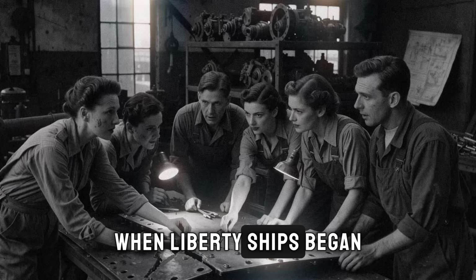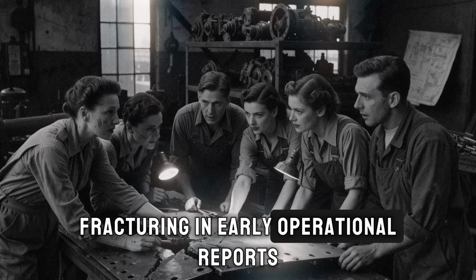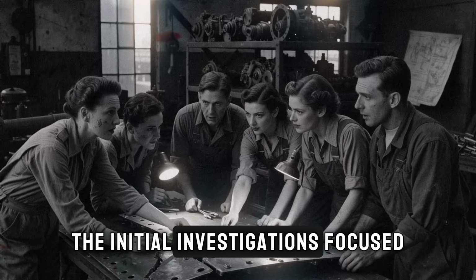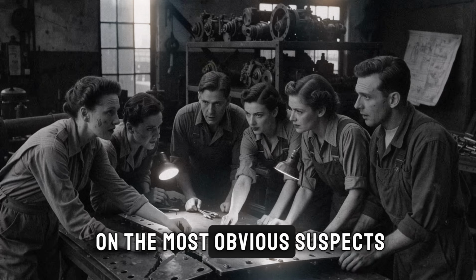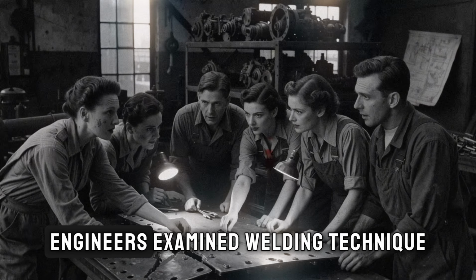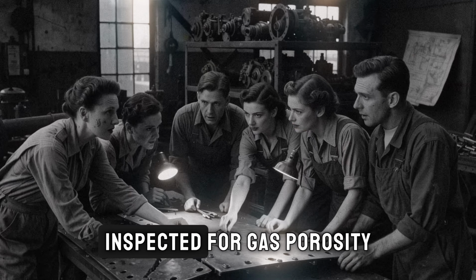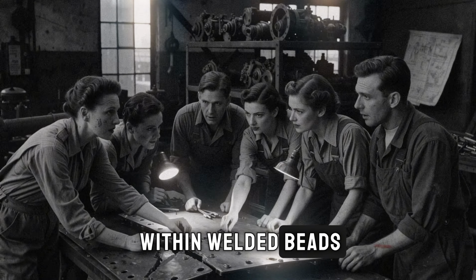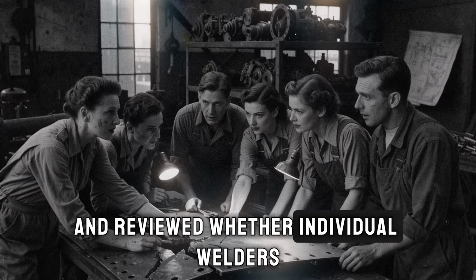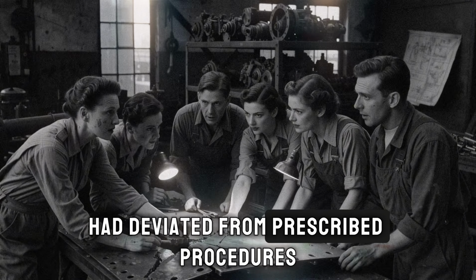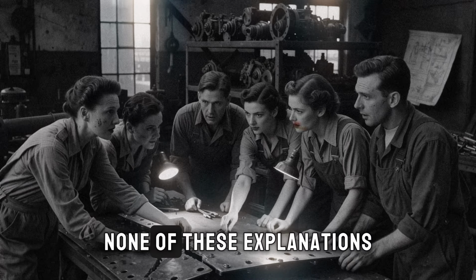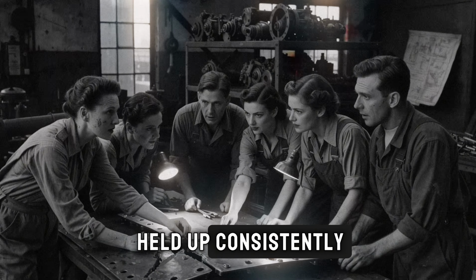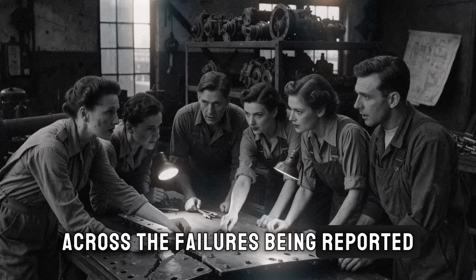When Liberty ships began fracturing in early operational reports, the initial investigations focused on the most obvious suspects. Engineers examined welding technique, inspected for gas porosity within weld beads, and reviewed whether individual welders had deviated from prescribed procedures. None of these explanations held up consistently across the failures being reported.